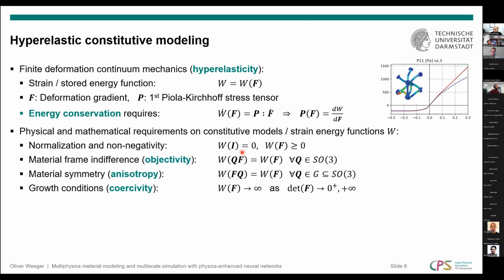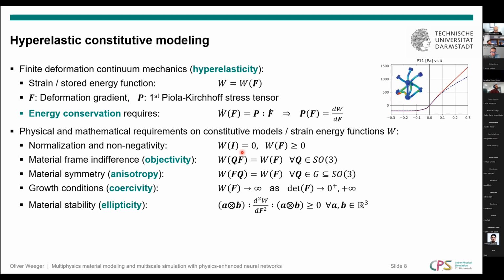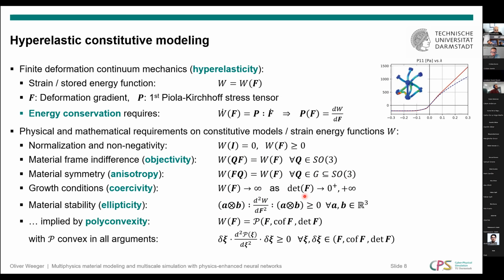So if you have infinite compression or infinite tension, your energy should go to infinity. And then also importantly, there should be material stability, which is ensured by the ellipticity condition, which means basically that this expression over here, which is very difficult to verify, should hold. That is why people came up with the concept of polyconvexity, meaning that when you formulate the W as a function in terms of F, the cofactor of F and the determinant of F, it should be convex in all the arguments.